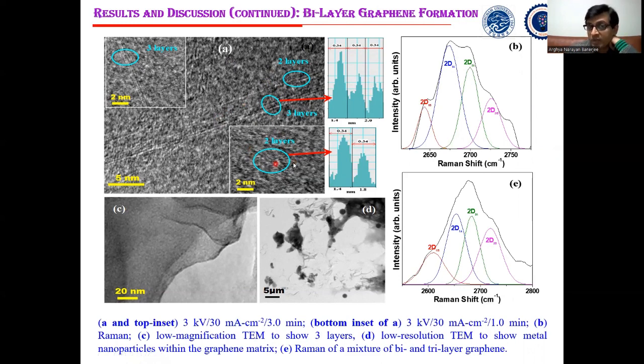So here also we checked the lattice spacing, which is matching with the d-spacing of graphene layers, which is 0.34 nanometer, and this is showing the typical Raman spectra of the 2D peak of a two-layer or bilayer graphene, which is clearly showing 4 components: 2D1B, 2D1A, 2D2A, 2D2B. 4 peaks are clearly observed. This is the signature of a bilayer graphene.